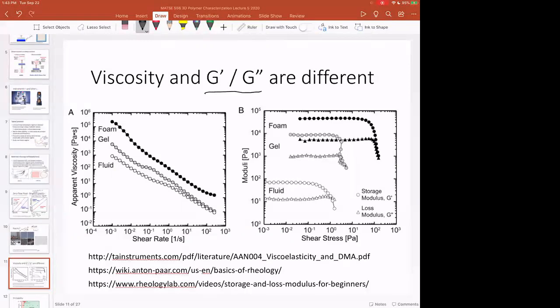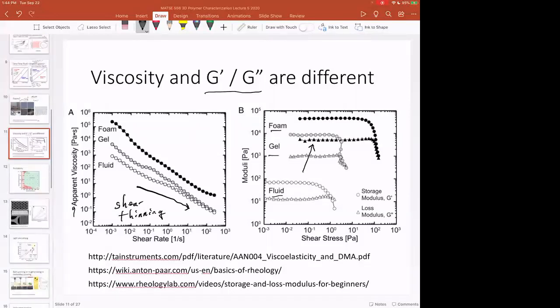modulus. So remember G prime and G double prime. Sometimes you see E prime and E double prime are the modulus of various, well, whether it's foams, gels, or fluids in this case. And then the apparent viscosity. So once this is flowing, you can see the shear thinning behavior because as the shear rate goes up, the viscosity goes down. So these are shear thinning. Okay, but since there is a constant modulus as a function of shear rate until you get to very high shear rate, these are considered Bingham plastics, so they can have this self-supporting behavior.